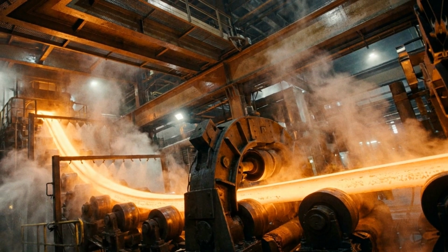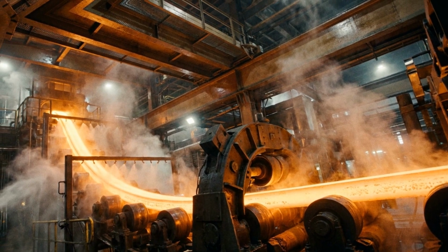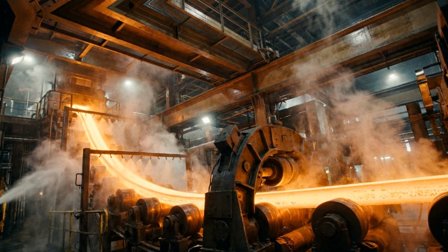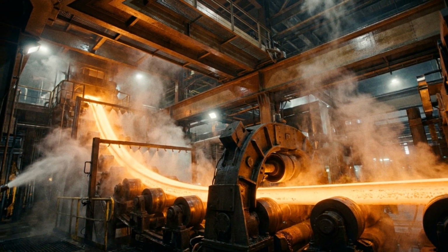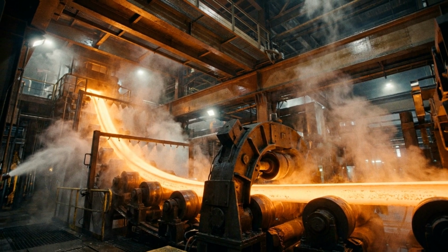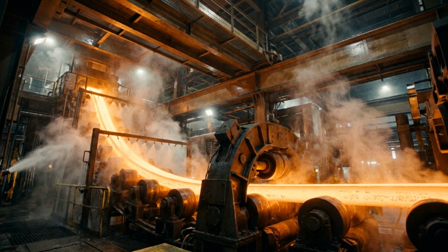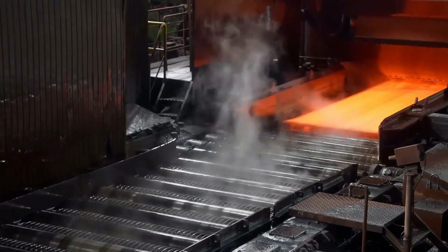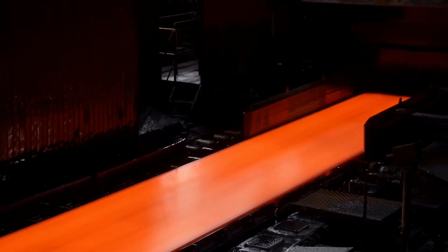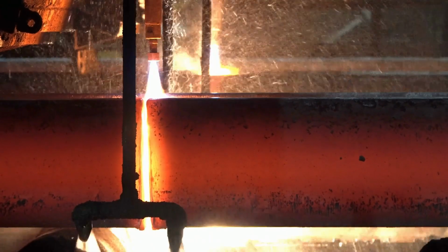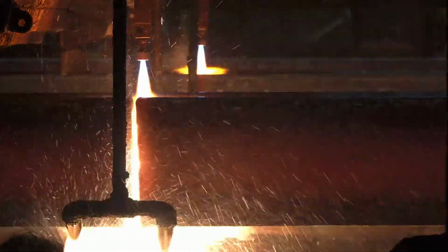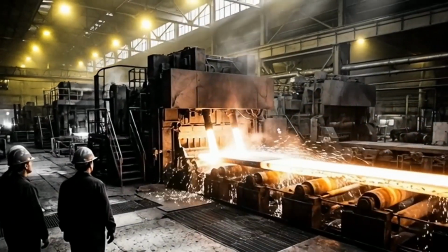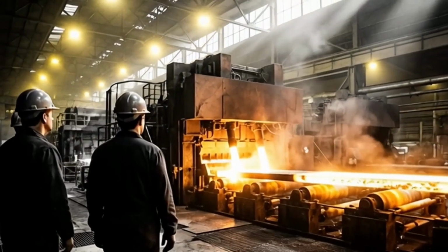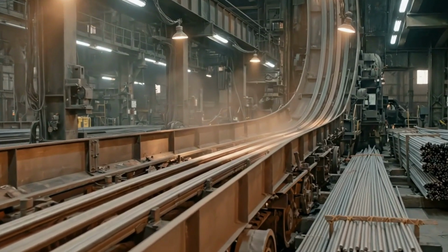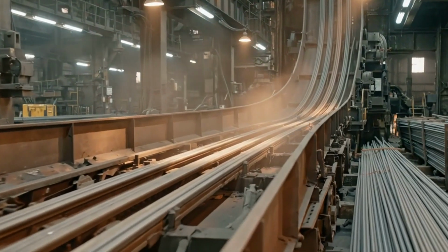The partially solidified strand, solid on the outside, molten in the core, is then withdrawn downward and curved through a series of water spray zones and support rolls that continue the solidification process while bending the strand from vertical to horizontal. By the time the strand reaches the horizontal runout section, it's fully solid. Torch cutters then cut it into slabs of the required length, and the slabs move off to the hot strip mill, or plate mill for rolling. The whole sequence, from liquid steel entering the mold to solid slab exiting the torch cutters, can span 40 meters of vertical and curved machine height.